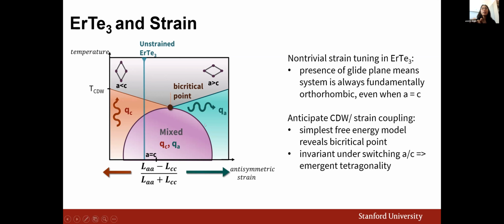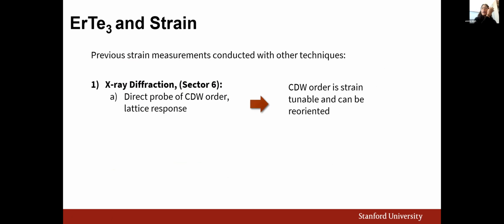So at this point, we expect an identical vanishing of the coefficients of our quadratic order parameter terms in a free energy expansion. And the remaining terms, at least up to quartic order in our free energy expansion, are actually going to be invariant under switching of the A and C axes, suggesting that at or close to this bicritical point, there actually is an emergent tetragonality in our system. Okay, so that's all good and well. We can write this model down, but there are a few things we actually need to demonstrate to show that this is indeed true.